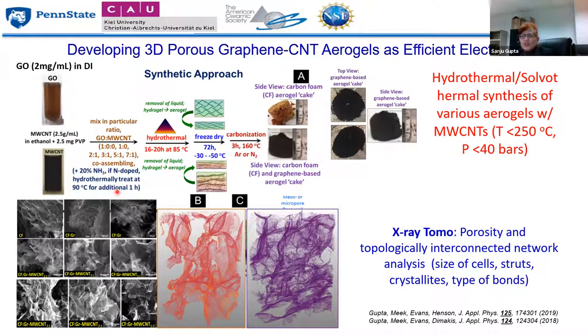And then we also did nitrogen doping to make it sort of a negative impurity in these graphene systems or aerogel system. And then you heat it for almost a day at a very low temperature of 85 degrees Celsius. And you get the hydrogels, and then you freeze dry, and then you carbonize it to have a better crystallinity. And you get what we call aerogel monoliths. So we use both hydrothermal and solvothermal synthetic approaches.